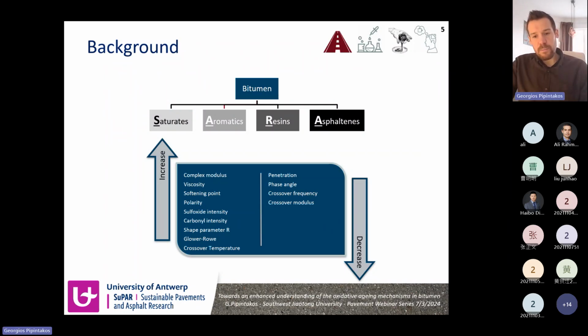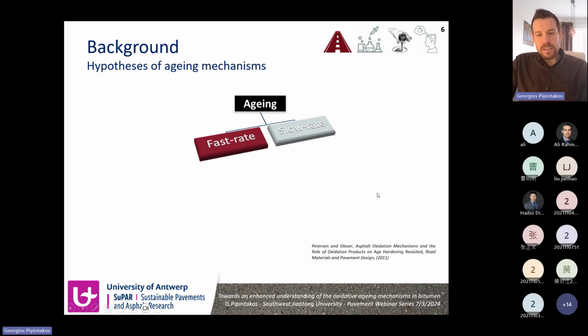And also we can see, for example, a decrease of penetration, which is an empirical property or a characteristic property of bitumen, and a decrease of phase angle with aging, and so forth. So this refers mainly in the literature to rheological properties and to some extent to basic chemical indices like the sulfoxides and carbonyls. However, it has not been studied thoroughly how all the chemical compounds in bitumen are affecting the aging mechanisms that have been hypothesized some decades ago.